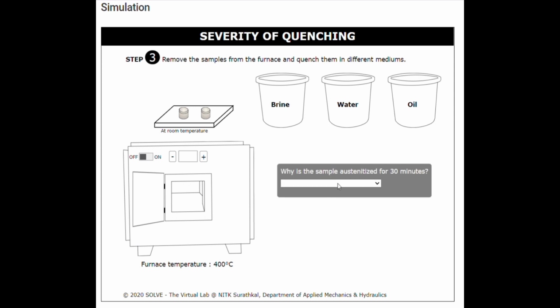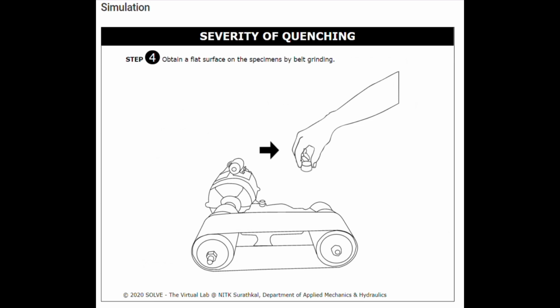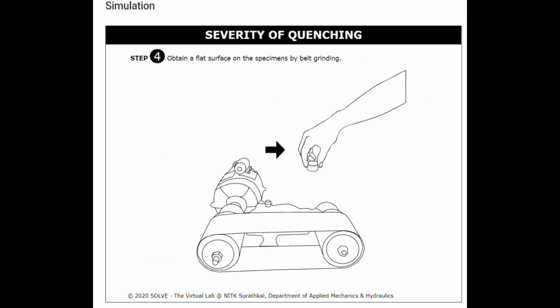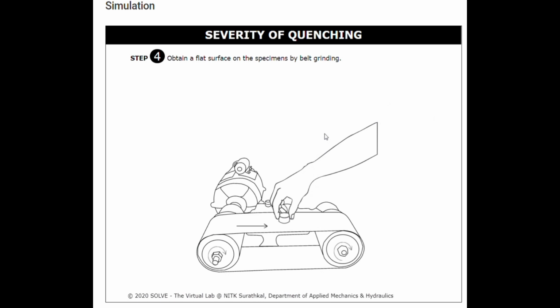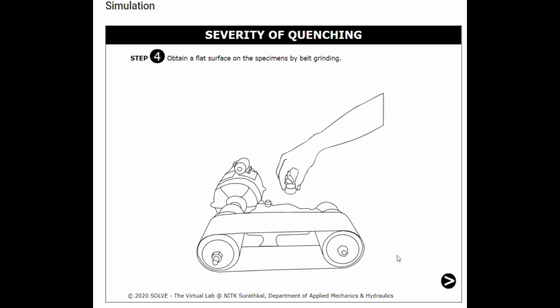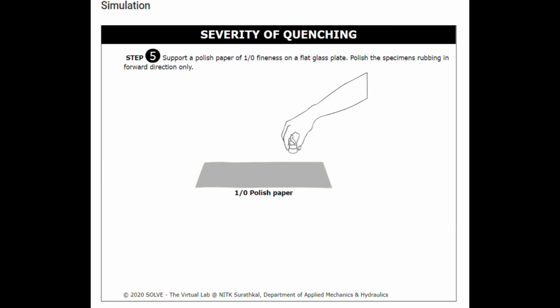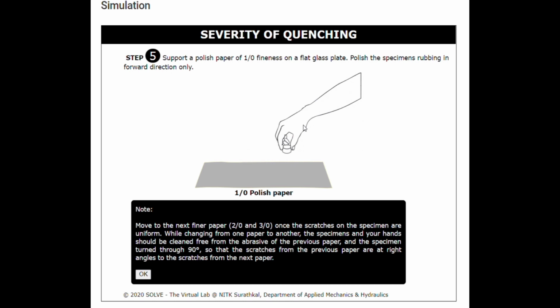Why are samples austenized for 30 minutes? To make the austenization uniform. In step 4, we obtain a flat surface on the specimen by belt grinding. In step 5, we support a polishing paper of 1/0 fineness on a flat glass plate. Then we polish the specimen by rubbing in the forward direction only. Then we move to the next finer papers, 2/0 and 3/0 fineness, once the scratches on the specimen are uniform.